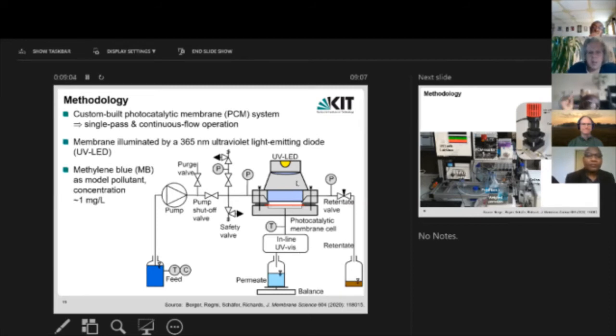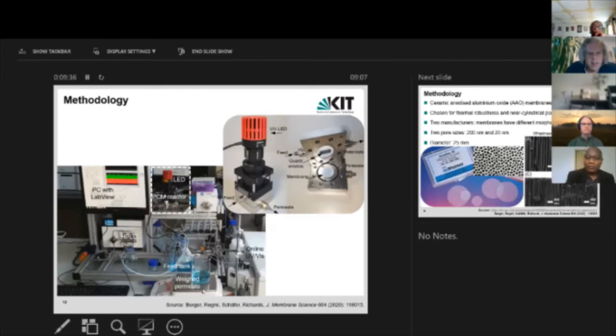And then from there, we can measure the amount of permeate, which is our clean water, using similar techniques to what Lars demonstrated for the orange dye. Here, just looking at the inline UV-Vis spectrophotometer to tell us how much light is absorbed in that region, thereby giving us a concentration of that dye, and deliberately shown here as being somewhat lighter in the permeate than was originally present in the feed. A schematic of the setup is followed by a photo here. The really interesting part is zoomed out on the right. There we have this high power UV LED in black and red, which is then bolted on top of a stainless steel cell. And on the very right hand side, you see the stainless steel cell opened up, and you can see that we have a place for a membrane here, and you can also see the quartz window on top.